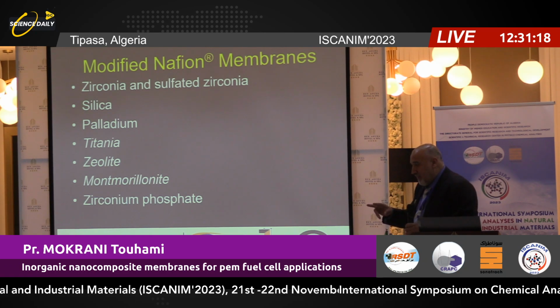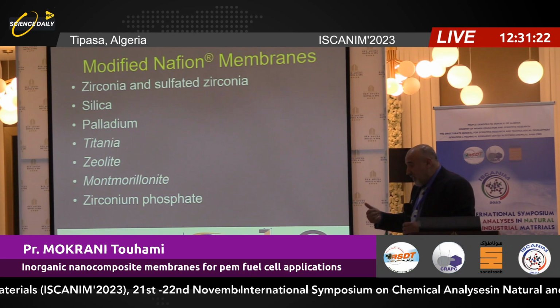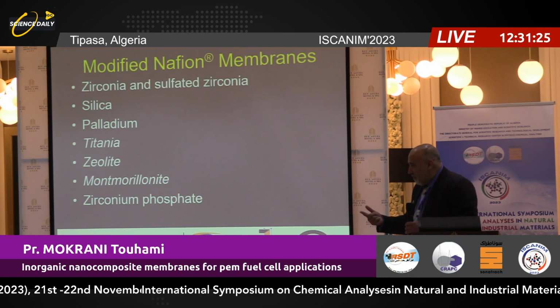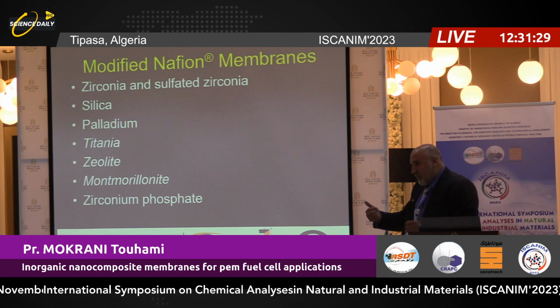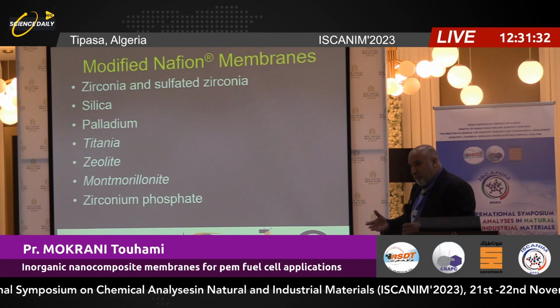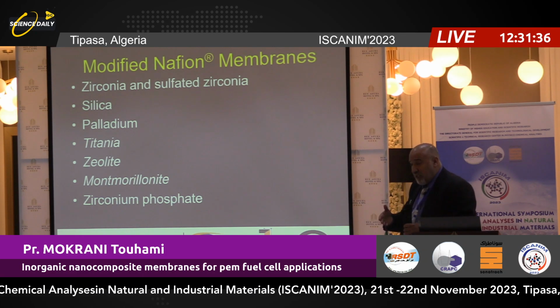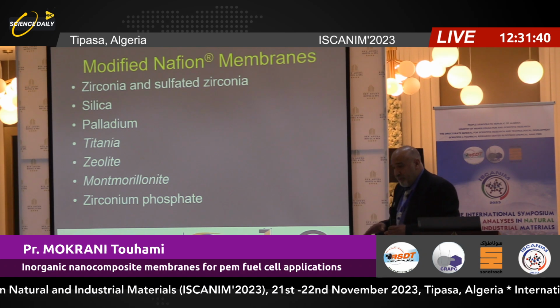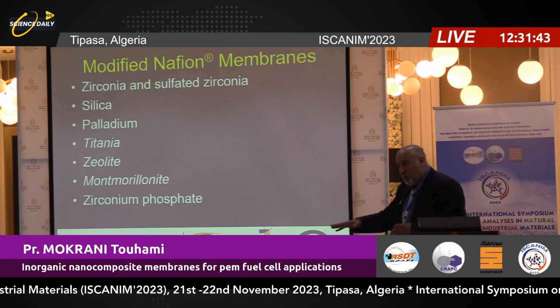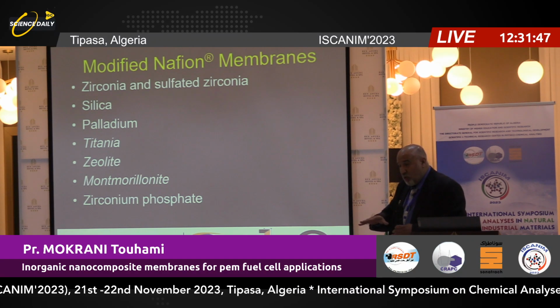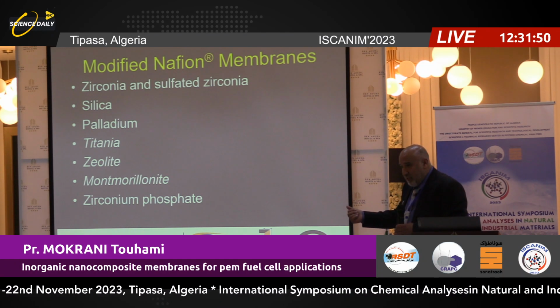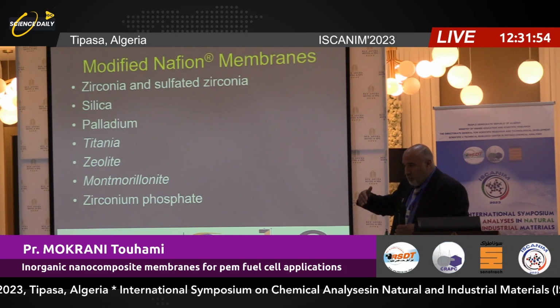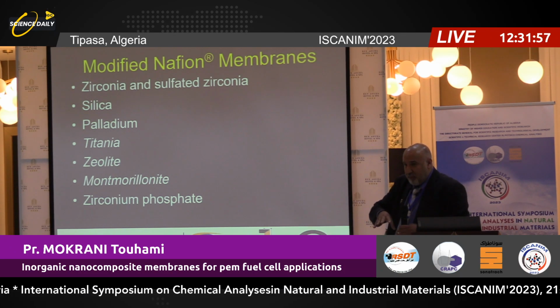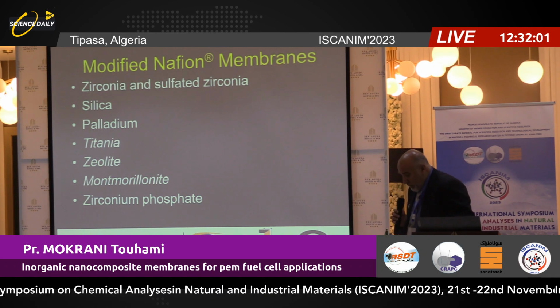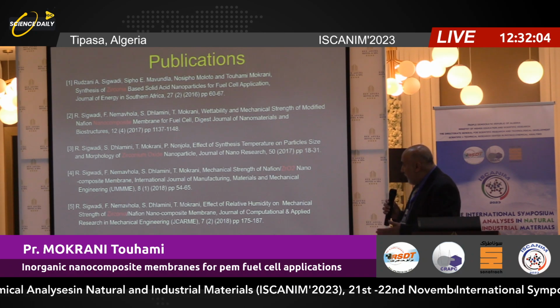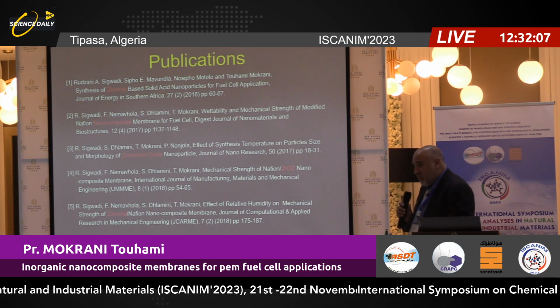So two things you need to look at. The materials must be less than 10 nanometers and the loading must be around 5%. These two conditions can satisfy. The reason for nano is the high surface area, but the nice thing about nano is the very good dispersion in the polymer. If you have nanomaterials, you can disperse them easily without agglomeration. The 5% loading is because of agglomeration: if it goes to 10%, you can see agglomeration in the polymer, and that's not good. So the presentation will stop here, but I am going to give you some of the publications and different materials we used.